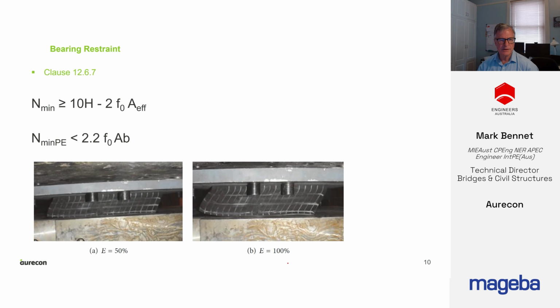Bearing restraint. There are two requirements for bearing restraint. The first equation is a straight friction consideration. For a bearing deflected to its shear capacity, equation 1 gives a coefficient of friction of about 0.17 to 0.20. This photo shows a bearing sheared to 50% shear strain. The second photo shows the bearing sheared to 100% of the shear strain.